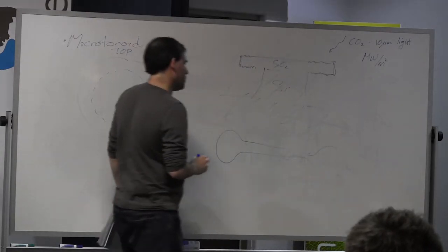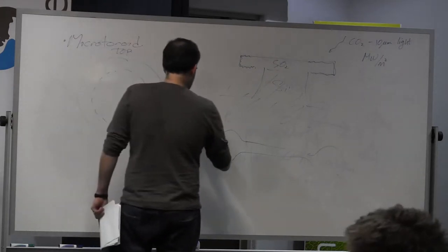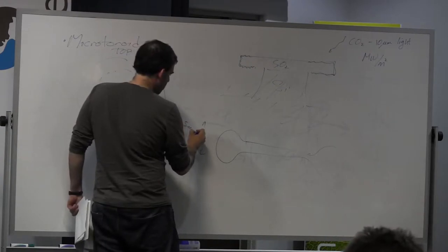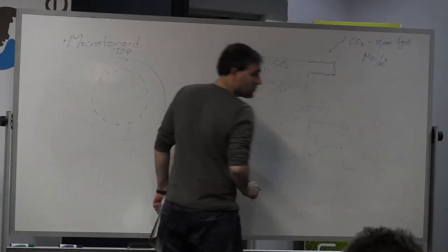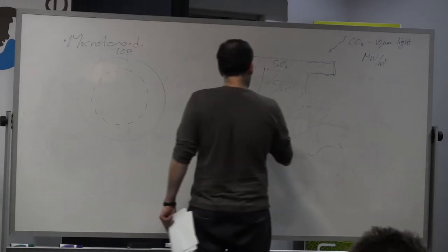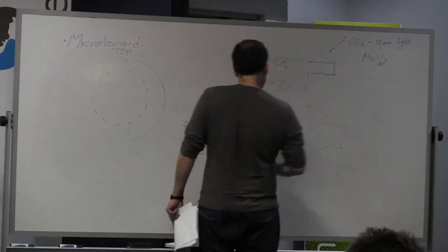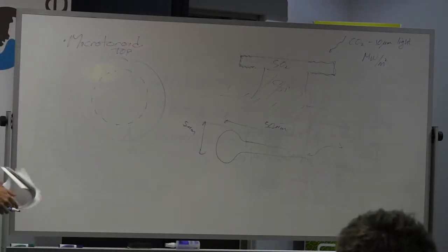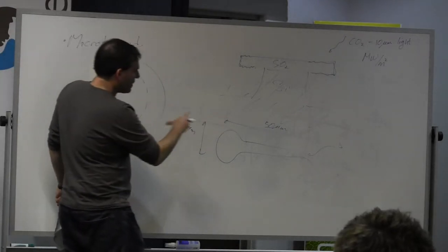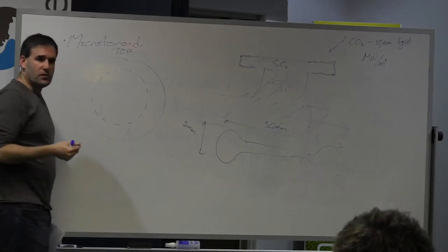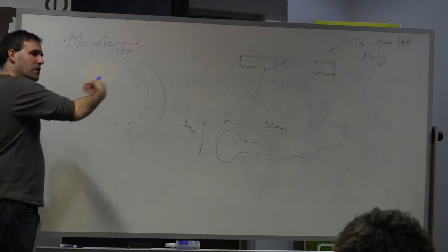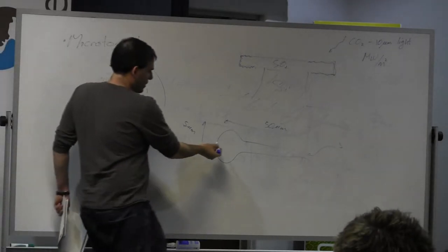That's sort of this cross-sectional shape, where this size is maybe 5 microns or so. And this dimension here, which defines the diameter of your toroid, is going to be tens of microns. And this thing turns out to be a lovely electromagnetic resonator now. The electromagnetic modes that propagate in this toroid are what are known as whispering gallery modes. They're modes that are trapped by the fact that they're internally reflecting on these surfaces of the glass.